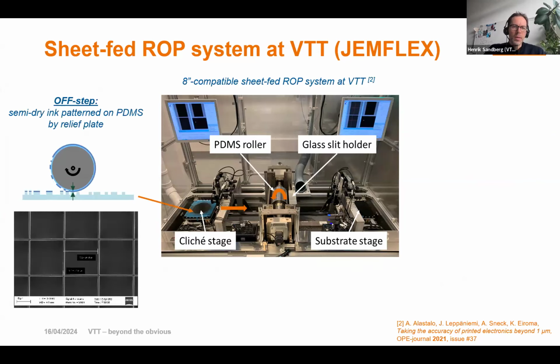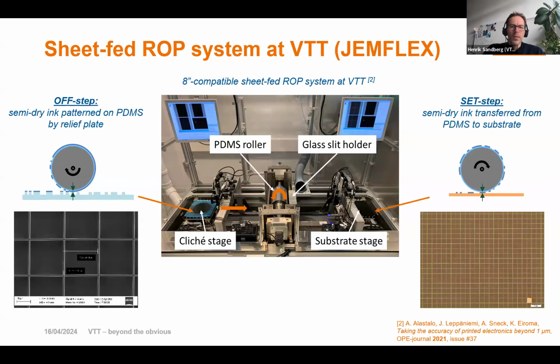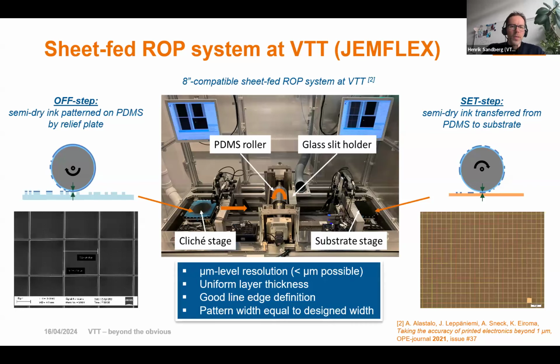So in the first step, the cliché stage moves beneath the roller and removes the material we want to remove from the PDMS. And then in the second stage, the other stage moves under the roller in the same way. And there are camera systems in both stages to make sure that the positional accuracy is what we require. Of course, if you do very small structures, also very high positional accuracy is required in this device. So as mentioned, we can reach a sub-micrometer resolution and also